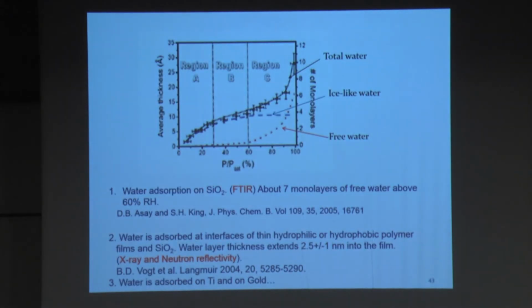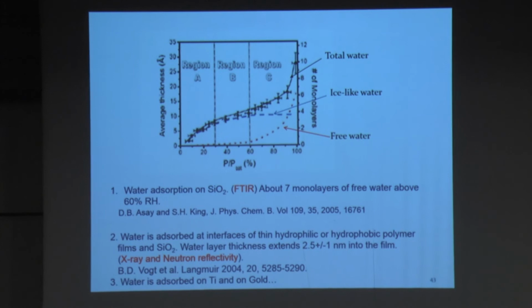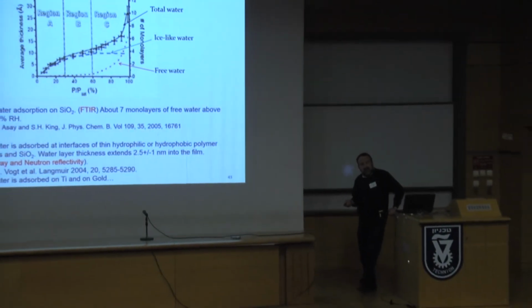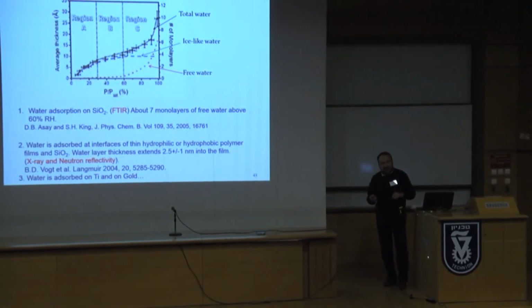Now, what's causing all this? We felt that this has something to do with the water that is absorbed either on the electrodes or on the SiO2 underneath or in the film itself. Well, people have shown by studying FTIR that on silicon dioxide above 60% of humidity, first of all, there's an ice-like water, about 4 monolayers, that is formed. However, from 60% up, there's free water, up to something like 7 or 10 monolayers of water. That much water at high humidities can do many things, and I'll show you in a minute. So we felt somehow that this is related to water. Also, people studying polymers, either hydrophilic or hydrophobic, have found that water is absorbed underneath the polymers at very high humidities.